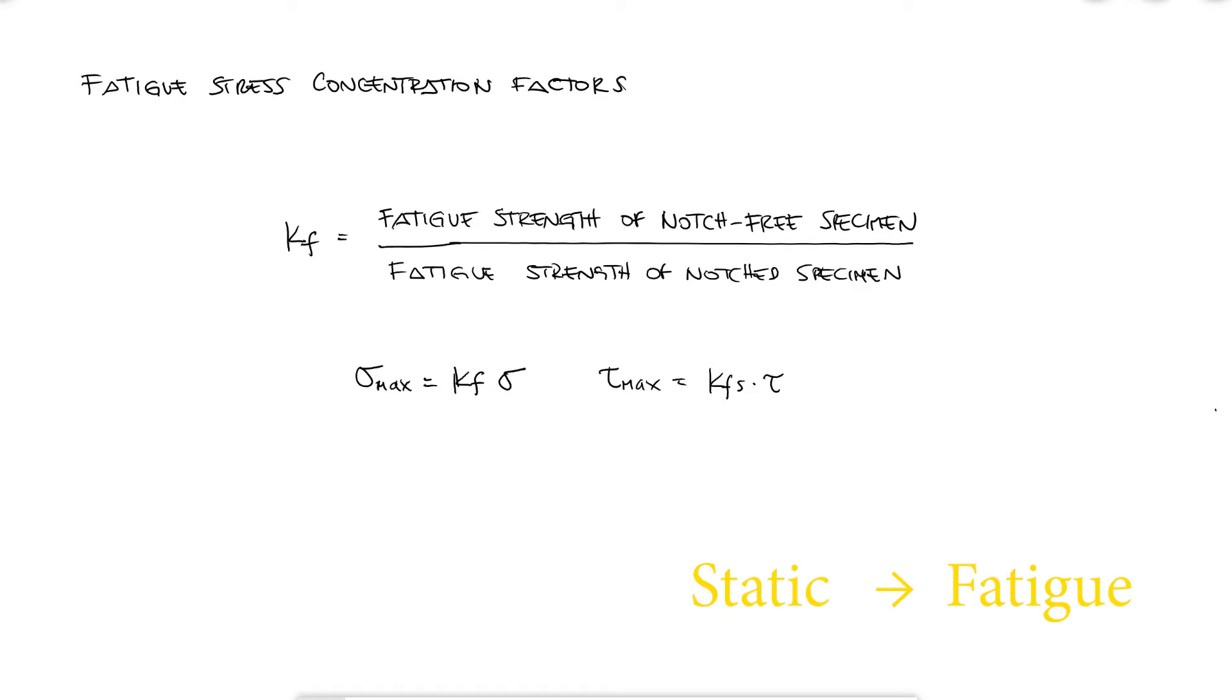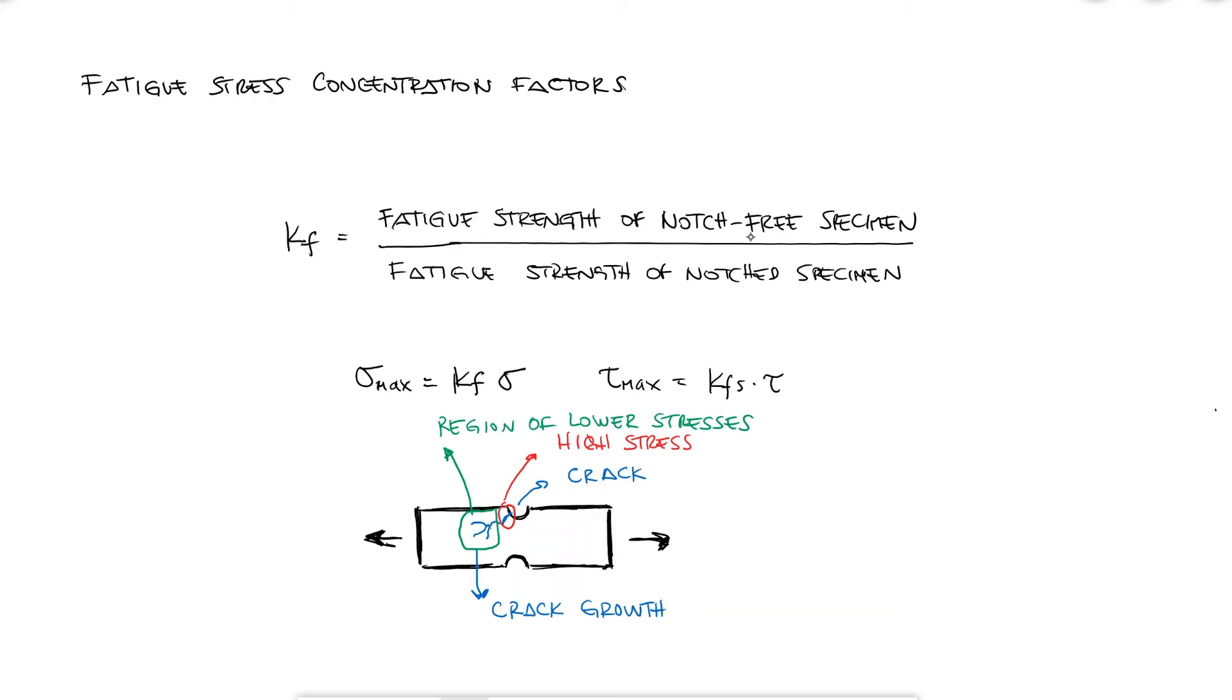The fact that the sensitivity is reduced when going from static to dynamic loading, that is, from static to fatigue analysis, comes mainly from the fact that the notched stress affecting the fatigue life is not the maximum stress at the notch, but instead it's the average stress acting over a volume of material close to the notch. Adding to this, any crack that is in fact initiated at a notch will be growing into a region with stresses that are much lower than at the stress concentration. However, not everything about why the effective stress concentration being lower for fatigue is fully understood.